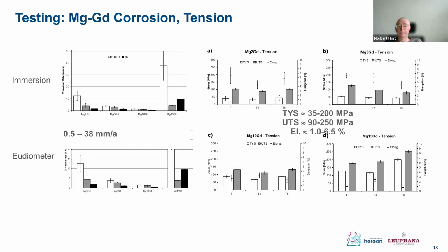And the same is when you take tensile testing as an example. Again, you can work on the property profile simply by working on the composition and, in this case, on the T4 treatments. If you want to have a high corrosion rate, okay, make it accordingly. And if you need a low corrosion rate, okay, follow the procedure right away with the composition and the processing.